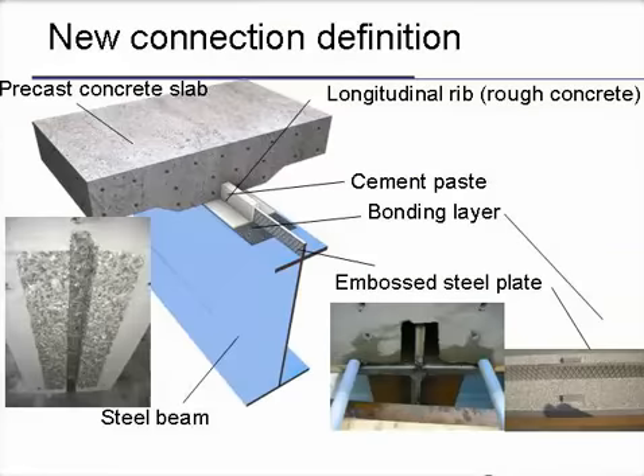So we looked at a connection that looked like this, where we have the steel beam, the precast concrete slab, and now we put over the steel beam an embossed steel plate like this, welded. Then we have also, in addition, a bonding layer. It's not obligatory, but we made it this way in this case to also improve the roughness of the top of the beam. It's an epoxy layer with sand. And then you put here a cement paste, a grout, to connect the whole thing. In order for the grout to connect both very well, you also do some water jet treatment of the rib here in the precast concrete slab to have good roughness. And here the tubes are to prevent the grout from going out.